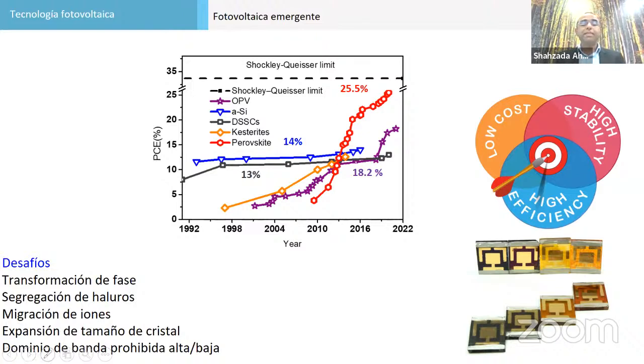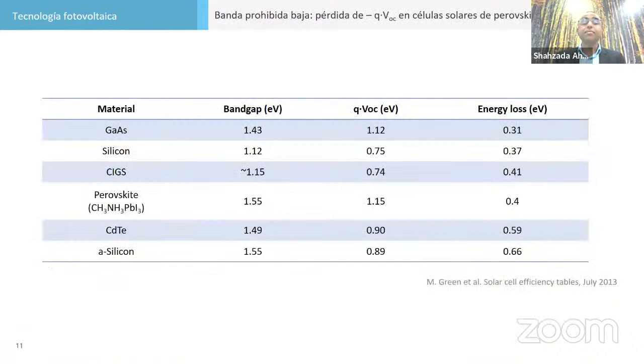And if you take a mixed halide, then you have high band gap and low band gap domains. The pure methyl ammonium lead iodide is a dark color, but if you mix iodide with bromide, it becomes yellow and orange color. This is also good for BIPV application. You can put them on your window application, because they are very semi-transparent. They give you efficiency of 10 to 12% here.